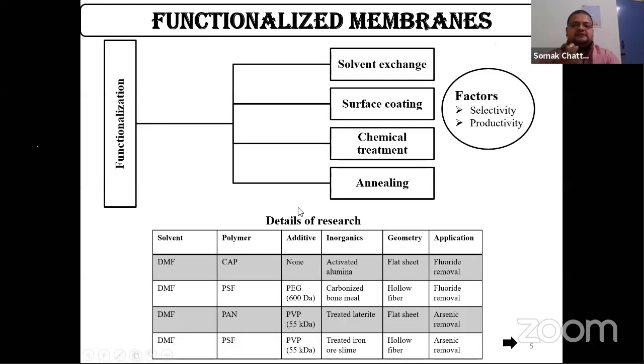Now, in our research, we fixed the solvent because it was the most available solvent in the market, that is dimethyl formamide. And we used all types of biocompatible polymers in this case. Biocompatible polymers don't have any acute toxicity with human cells, and don't produce any harmful byproducts. Most of these are cellulose acetate phthalate, polysulfone, polyacrylonitrile. And in this case, we used additives to increase the pore size and to add extra mechanical strength to the membrane. Mostly these additives were polyethylene glycol and polyvinyl pyrrolidone.